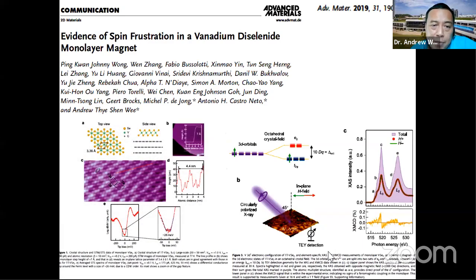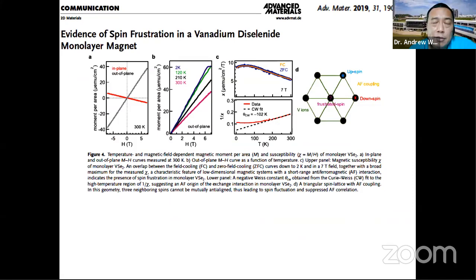And these are the STM. We see charge density waves, so there's a certain periodicity. And STS shows that it's metallic, or at least there's a very small gap. So we have the metallic 1T phase, and it doesn't seem to be magnetic. I must say the XMCD is important because you can get magnetic information at the element-specific level.